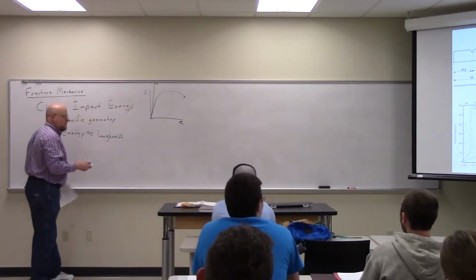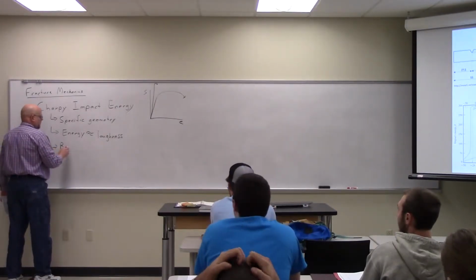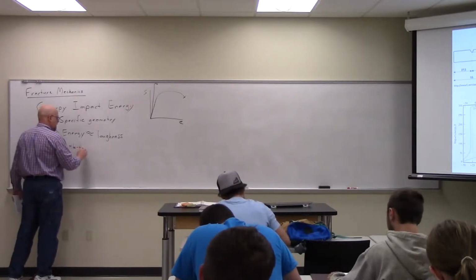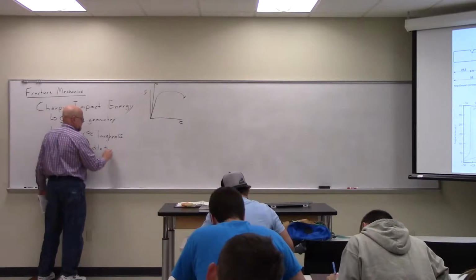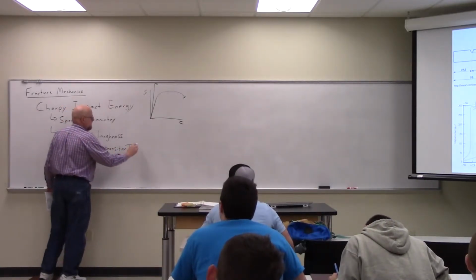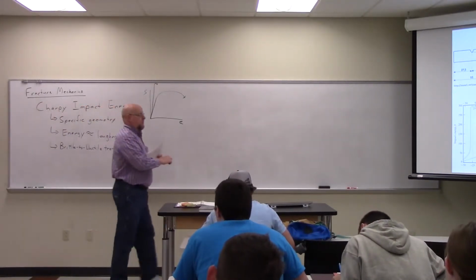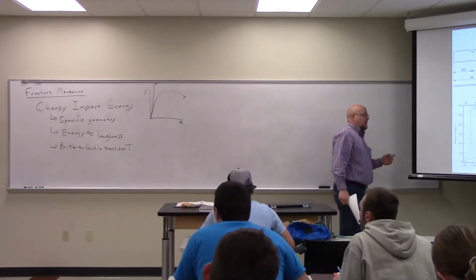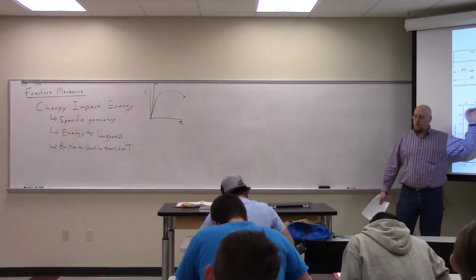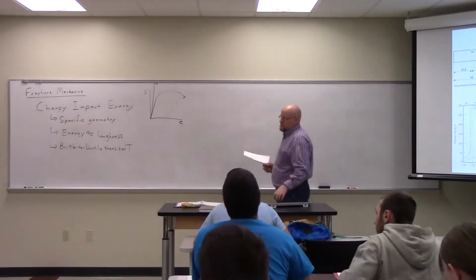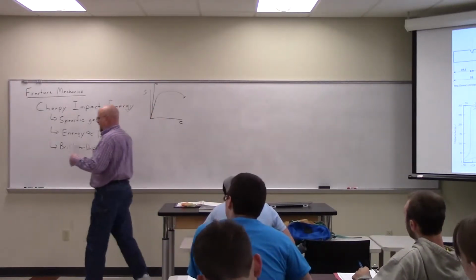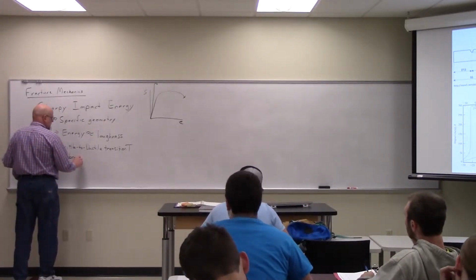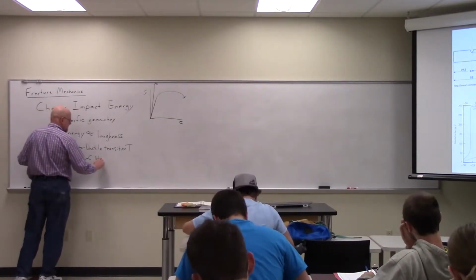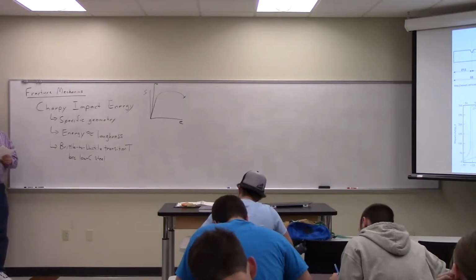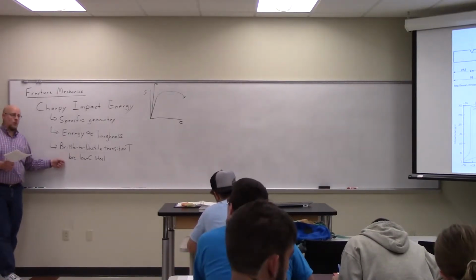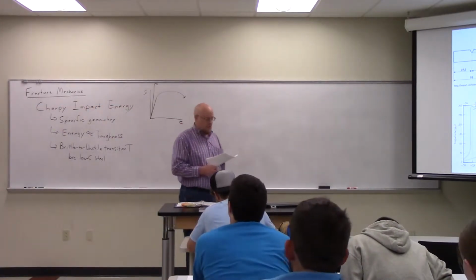Okay? What we have here is what's called a brittle to ductile transition temperature. So there's a temperature, and for that particular material it is 25 degrees C, below which that material behaves brittly. But above it, it behaves ductilely. So does that exist for most solids? It does not exist for most solids. This is especially true for BCC low carbon steel. It's not the only thing that happens in it, but it's especially true for BCC low carbon steel, which, it turns out, is what they made Liberty ships of.